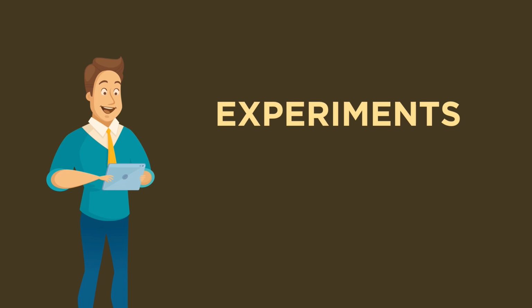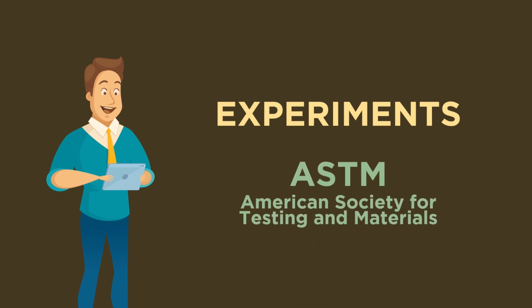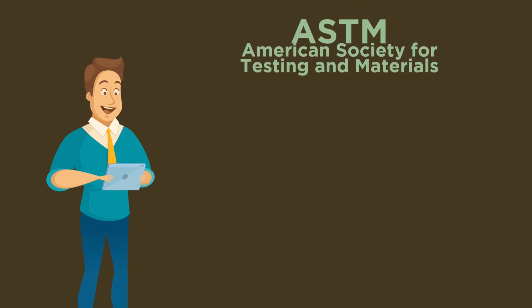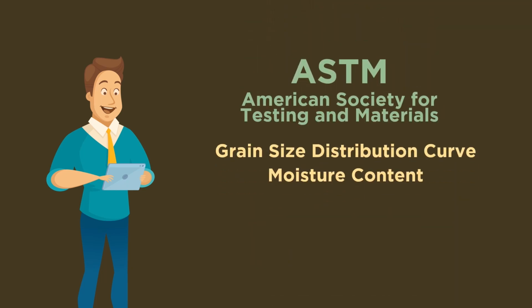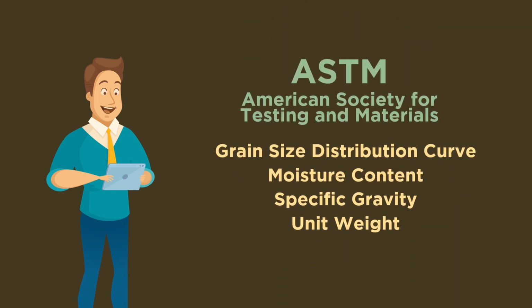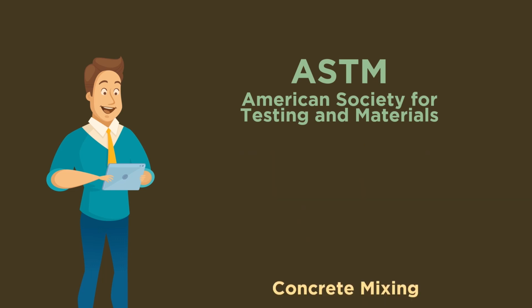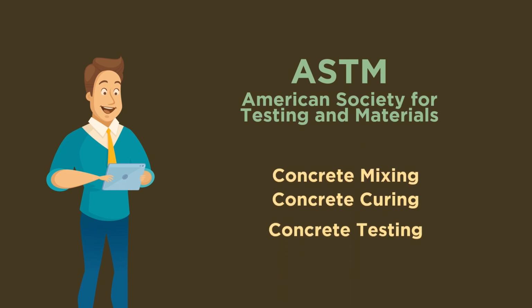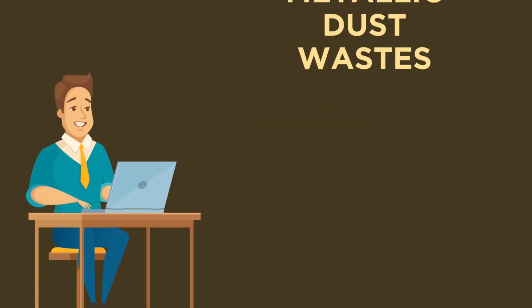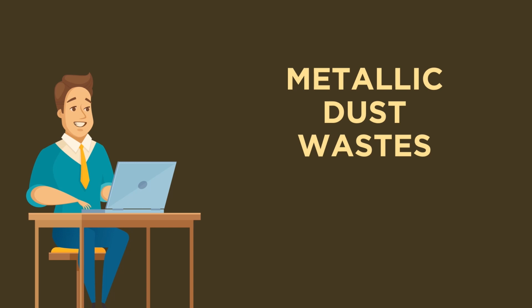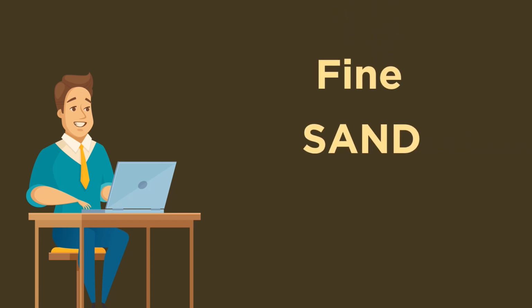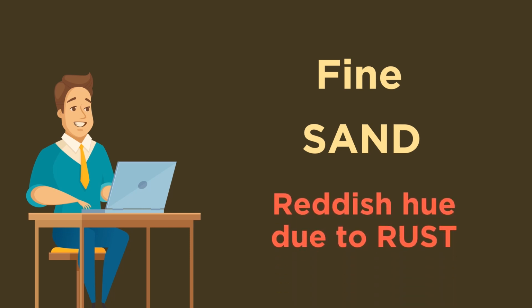In our study, all the procedures were done following the ASTM standards. We did the ASTM grain size distribution curve, moisture content, specific gravity, unit weight, absorption, concrete mixing, concrete curing, and concrete testing. So basically, we did everything in ASTM standards. The metallic dust waste used in this study was gathered locally from the blacksmith houses or panday in the Philippines. The metallic dust waste gathered is observed to be fine in texture, which is comparable to sand, and has a reddish hue due to the presence of rust.